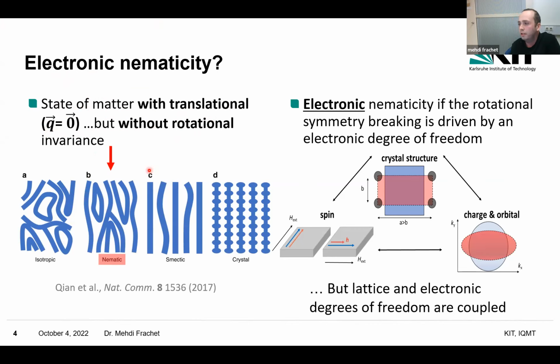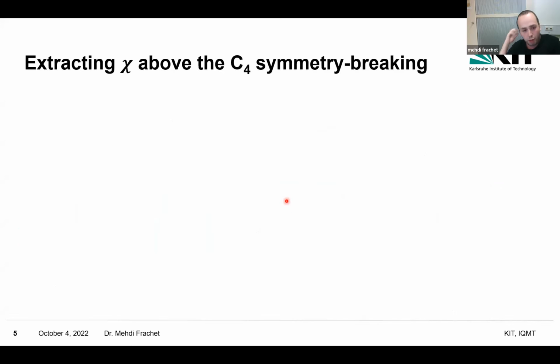What we are really interested in is not only nematicity, but electronic nematicity, when the rotational symmetry breaking is driven by electronic degrees of freedom, like spin, charge, or orbital. It's not so easy to say that a system is an electronic nematic system, because as soon as the rotational symmetry of the crystal lattice is broken, you also have anisotropies that emerge in the spin, charge, and orbital electronic degrees of freedom. There is one way to deal with that problem, which has been used quite extensively in the case of iron-based superconductors, which is to look at the electronic nematic susceptibility above the symmetry breaking.